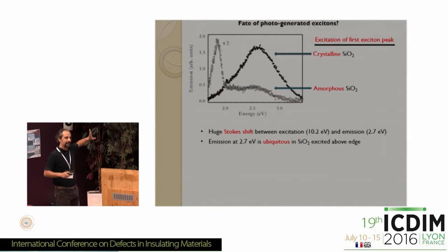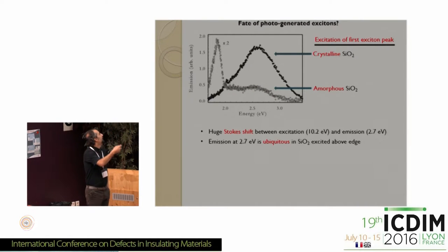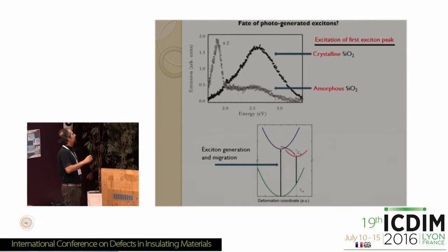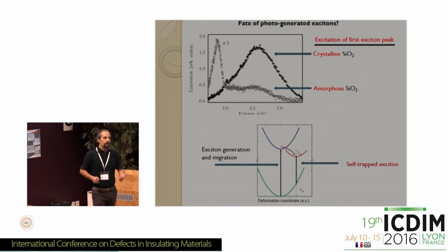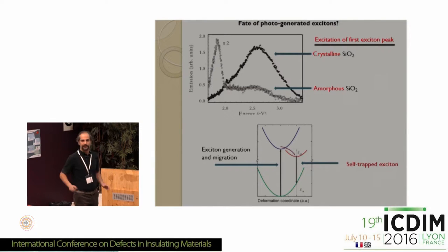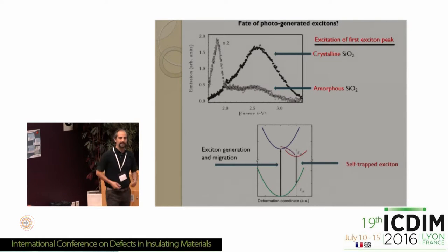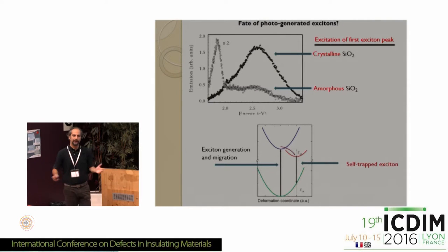Now, forget for a moment the additional band at 1.9 eV. Let us focus for a moment on this one. This band was already known before our studies, and it's basically the band of the self-trapped exciton in SiO2. You can recognize this because, first of all, this band is observed in any kind of SiO2, it is ubiquitous. It can be observed not only under light illumination above the absorption edge, but also under X-ray exposure, for instance. So it's observed everywhere. It's not associated to any kind of defect or impurity. It's inherent to the system.